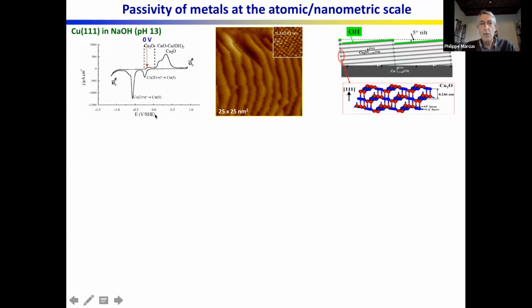Copper 111, which is a single crystal to avoid the effect of grain boundaries, which we investigate in other studies. We can, at the same time, draw the cyclic voltammogram, and at the same time, we can observe the surface in situ in the electrolyte, and we can do it with very high resolution, because here you can see an image which is atomically resolved. Each of these maxima here, the bright spots, correspond to atoms.